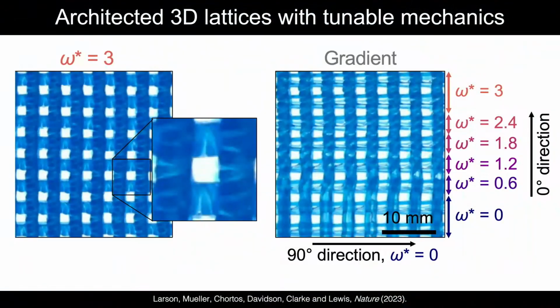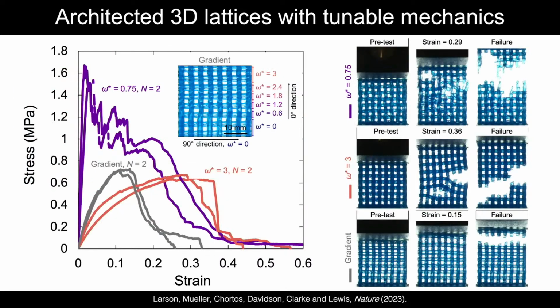And of course, not surprisingly, we extended this into lattice-like architectures. So not just filaments, now we're building lattices. Both ones here where you can see the stiff and soft at a normalized rotation rate of 3, or gradients where we're tuning across the architecture the stiffness and strain window by changing the rate at which we rotate the nozzle as we're printing. And with that, then again, in these three-dimensional objects, we have a very large landscape of responses that we can tailor in.